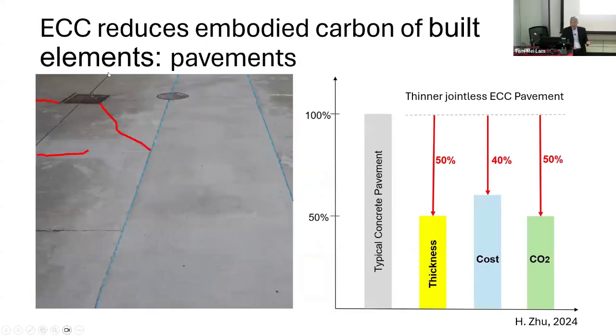Here's another example. This is comparing conventional concrete pavement, which shows the cracks there, and this piece here, where we use ECC to replace the conventional concrete pavement. In this case, on the surface it looks the same, no difference, but inside we actually reduced the thickness of the pavement by 50%. Why is it possible to do that? Because the flexural strength of ECC is more than double that of normal concrete. So no steel reinforcement, lower thickness, in fact, no expansion joints, no cut joints required. The material ductility takes care of that.